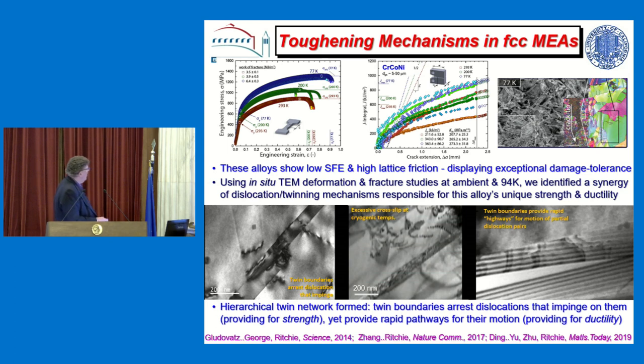So we looked at these quite early on, and this is looking at a three-component material with chrome, cobalt, nickel. And what we find is, this is the stress-strain curve, and you can see we go from brown, green to blue, room temperature to liquid nitrogen temperatures. As the material gets cooler, it gets harder. Well, we kind of expect that, but it also gets more ductile. Most materials get more brittle at lower temperatures, but these get more ductile, and they have incredible ductility at liquid nitrogen temperatures.